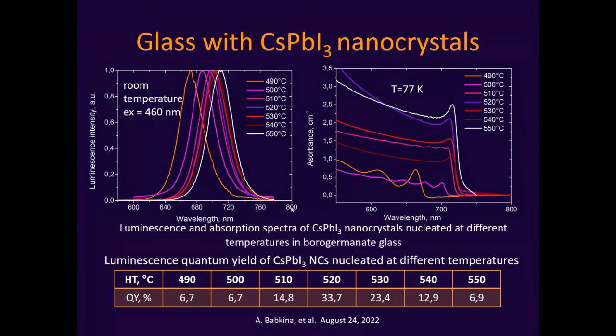It means that if we are working, for example, with the bromide crystals, we can vary the luminescence from like 450 nanometers up to almost 550 nanometers, so by 100 nanometers in the visible spectrum. If we are talking about iodide nanocrystals, as here, you can see that we vary it almost by 100 nanometers in the red region of the spectrum. And that is very good for us.